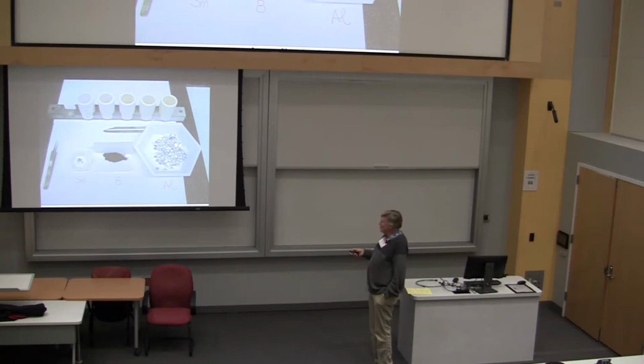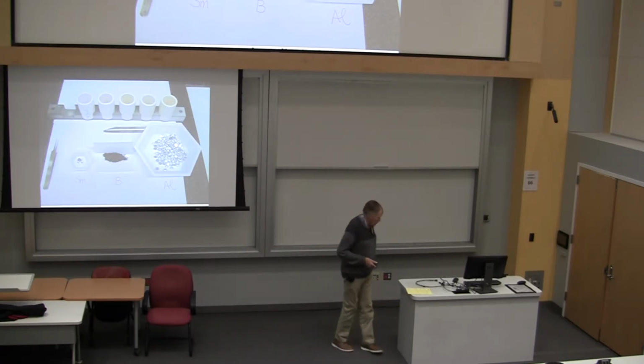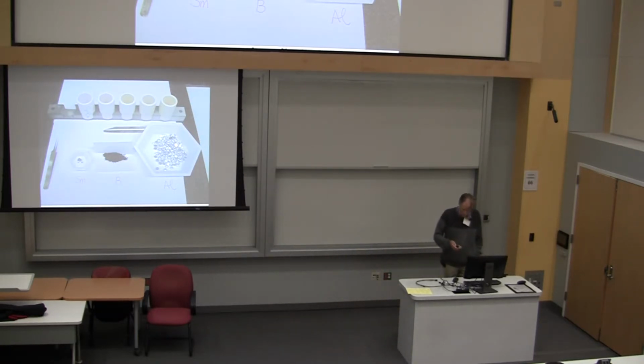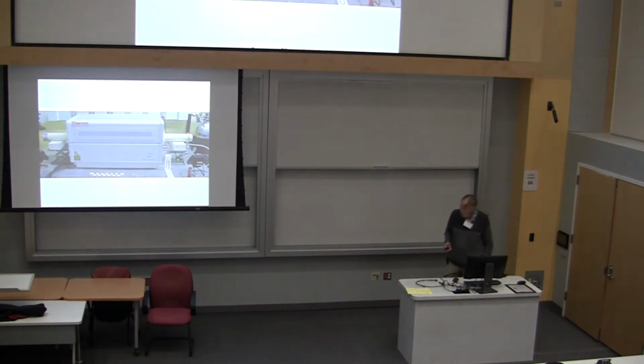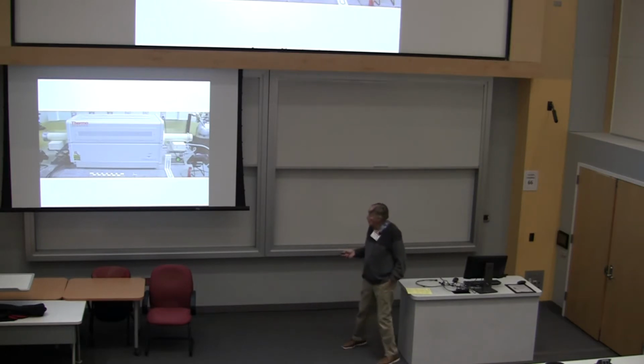But you see here is a holder for holding a set of crucibles, just machined out of graphite and then outgassed, because graphite tends to have a lot of crud in it. And then this can fit into a horizontal tube furnace. So the reason for going vertical was that you couldn't easily stack the average 50 ml crucible into a tube. But if you have a large enough bore tube furnace, you can do it.